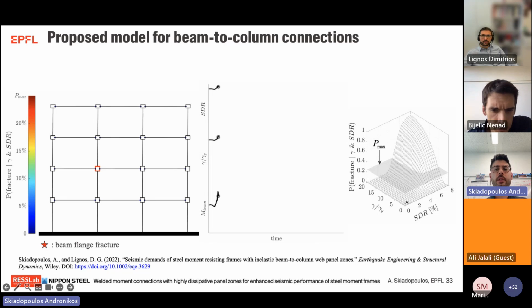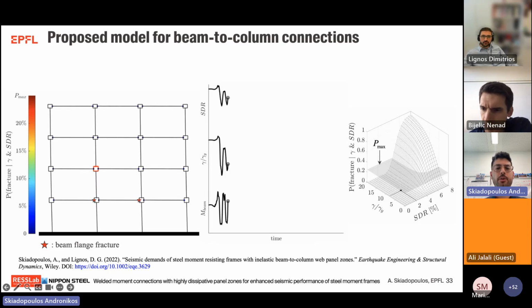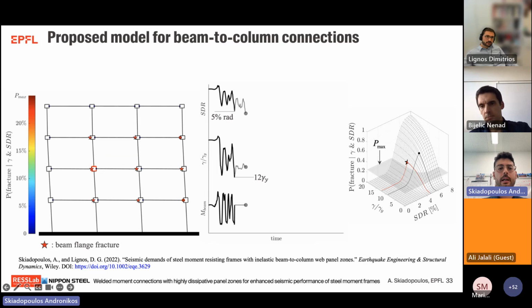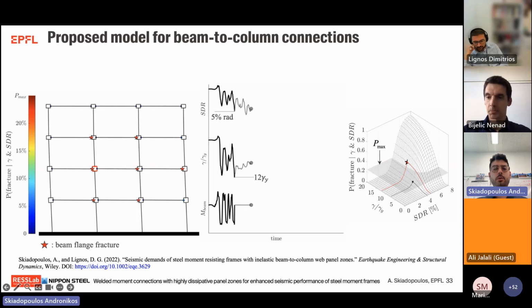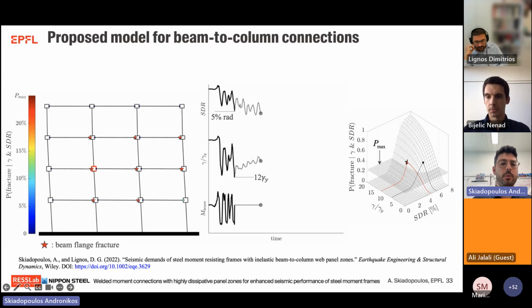Due to the highly inelastic panel zone designs, we explicitly consider the fracture potential in the connections, as described in the bivariate lognormal distribution that I also showed before, that is shown on the right side. So what we do in the analysis is that at each time step of the dynamic earthquake loading, we calculate the fracture potential for all beam to column connections by considering the panel zone shear distortion and the story drift ratio at that time. So if the calculated probability of connection fracture exceeds the threshold that we set, then we assume that the connection loses its moment carrying capacity, as characteristically shown in the middle of this slide.